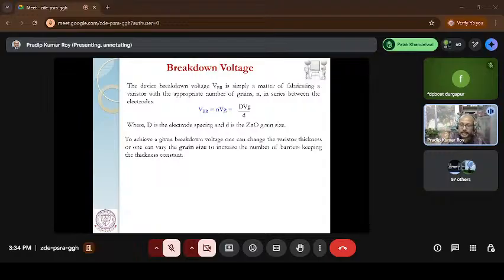If I want to break one bismuth oxide layer, I need 3 volt. Okay, so if the rating of the block is 3.6 kV, that means there are 1200 grain boundaries acting as a varistor. Because to break one grain boundary, I need 3 volt. So if there are 1200 grain boundaries, I need 3600 volt. Then only the rating of the block comes to 3.6 kV. Otherwise, if the grain boundaries increase, then the rating of the block also increases.